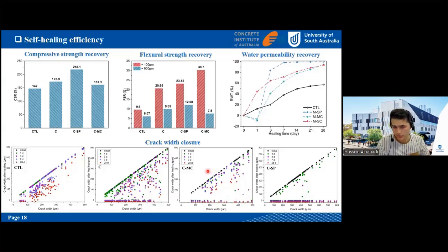And addition of two other supplementary materials to the capsule core increases its closure rate. And in the samples where we had super absorbent polymers, the crack width it can heal was around 800 micrometer. So it can actually heal very large cracks.